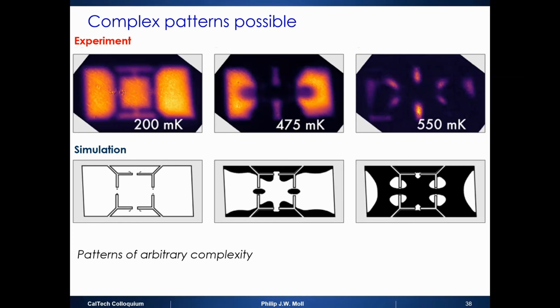Then the inverse problem is a little bit more complicated. Forward is straight out trivial. You make a bunch of slits, and then you can compare its simulations to the measurements. And this actually matches really, really well. For example, you get these isolated islands of superconductivity in the structure.